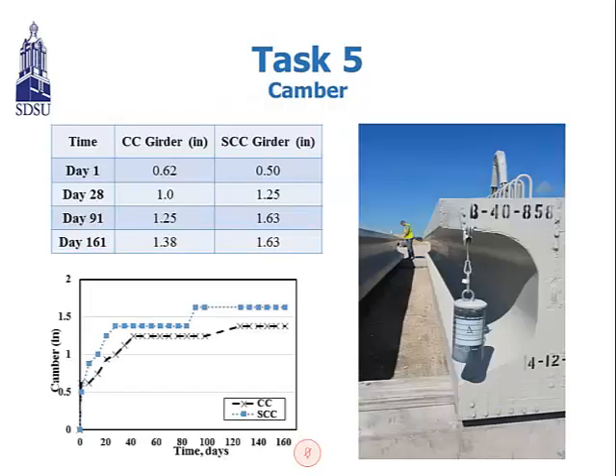And also we took a measurement of the camber right after the release, day one, and we get the camber 0.62 for the CC girder, and 0.5 for the SCC girder. And also we kept the monitoring of the camber as we did the prestress losses up to day 161. Also we summarized the data into the graph, camber versus time. And then we can see the similar trend between the CC and SCC in terms of the camber. And SCC has a little bit more camber change, but we can see the similar result.